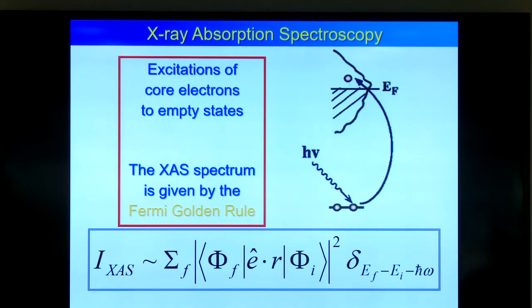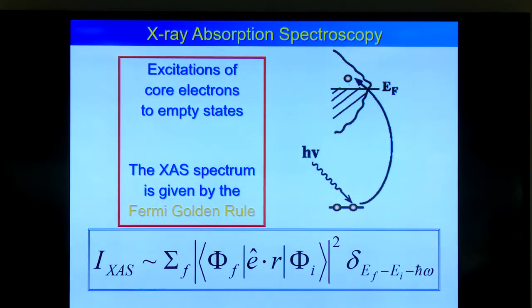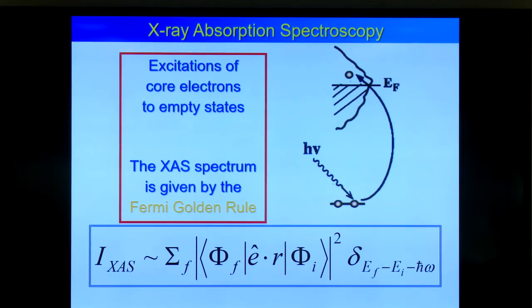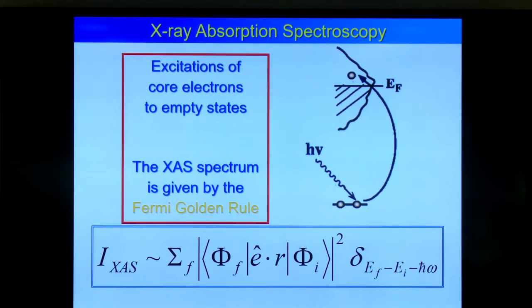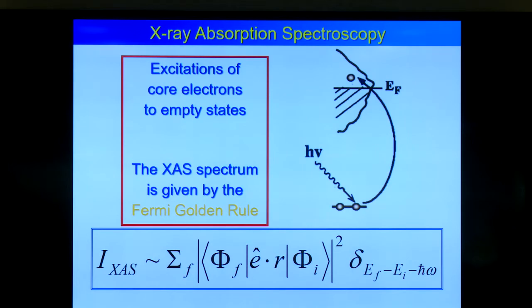So if we do X-ray absorption spectroscopy, we have to solve the Fermi golden rule. So that's the theoretical goal. So what happens with an X-ray? It excites a core electron to an empty state, and you have to calculate the transition of the initial state wave function, so the ground state of the system, to the final state wave function, so that's the excited state of the system with the core hole and the extra electron and the empty states. And then by solving that, you can try to interpret the X-ray absorption spectra.